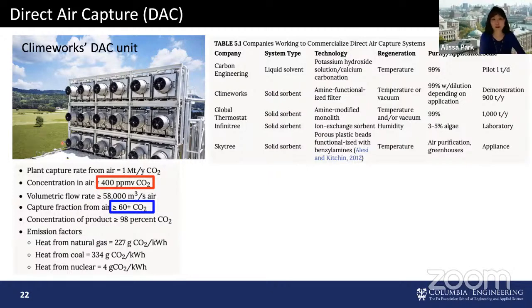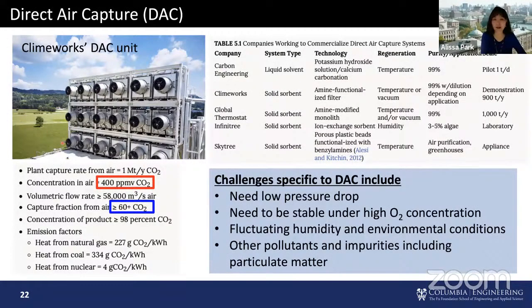Other challenges for systems and materials development are also interesting, because the amount of air you have to process to capture the same ton of CO2 is so much more. So it is not possible for us to compress all that air. You need to have very low pressure drop in any of your direct air capture systems. Also, you're capturing CO2 from a stream, which is air, that has high oxygen concentration. And because of that, the material inside your direct air capture system has to be very robust at high oxygen concentration, and having higher oxidative and thermal stability is very important for your materials for longevity.